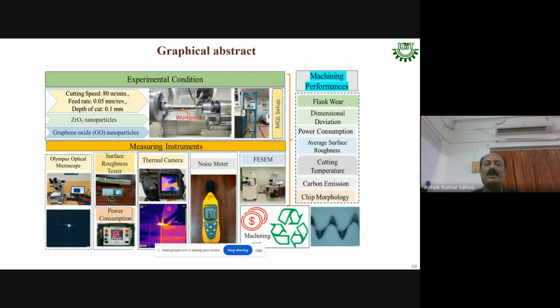So this is the experimental setup: the cutting speed is 80 meters per minute, feed rate is 0.05, depth of cut is 0.1, and 2 nanoparticles are used, ZrO2, zirconium oxide, and also graphene oxide. Machining performances are measured here. Comparative machining performances are observed for flank wear, dimensional deviation, power consumption, roughness, and cutting temperature. Also, we have measured the carbon emission and the noise emission, as well as chip characterization, done by many measuring instruments: microscope, surface roughness tester, IR camera, noise meter, scanning electron microscope, and a lot more. So this is more or less the experimental techniques and setup.